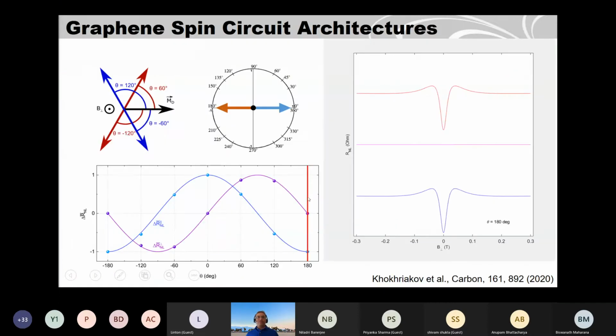And if we do that, we did a simulation of how this signal should look. If you are injecting spin at one point and detecting at several angles, so your detectors are situated at several angles on the graphene, you should see how the symmetric and anti-symmetric signals change. This information is required if you want to make a spin circuit, because nanomagnets may be sitting at different angles in a circuit. So that is quite useful, and it also practically works. These are the experimental data points we have here, and the lines are the theoretical fits.